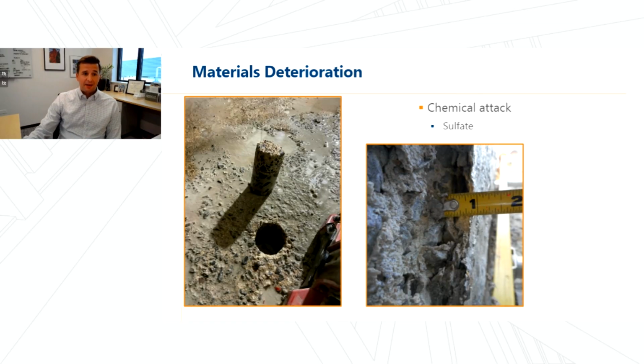One is sulfate attack, and this is very complex. It takes many forms. But traditionally, we think of dissolved sulfate ions that interact with cement to form expansive byproducts of gypsum and ettringite. And similar to corrosion, the expansive nature of this reaction can cause tensile stresses that result in a loss of strength, cracking of the concrete, and perhaps even spalling.